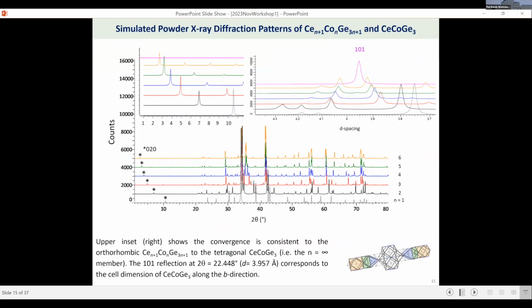Now, the thing is, when you have to grow single crystals, you really have to think about whether we can distinguish them. With these stacking subunits, it's very important to be able to say they all look the same. The crystals look the same. So one of the things we did was, if we zoom in, we have to carefully evaluate the powder diffraction pattern to really think about what the structure should look like, and whether we have the right phase or not.